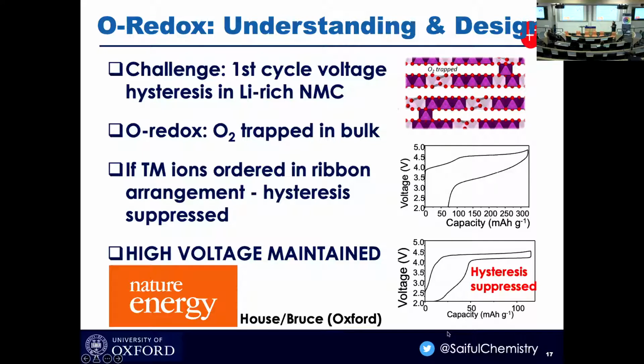They found that on charging, you have oxygen redox in addition to transition metal redox. What was the character of that oxygen redox? They found that it's molecular O2 trapped in the bulk, and that's shown as a schematic on the top right. So it's a very unusual mechanism. You've got molecular O2 trapped in the bulk. What's interesting is that on discharge, that O2 transforms back into O2 minus. But it's not a fully reversible process, and hence the voltage drop.